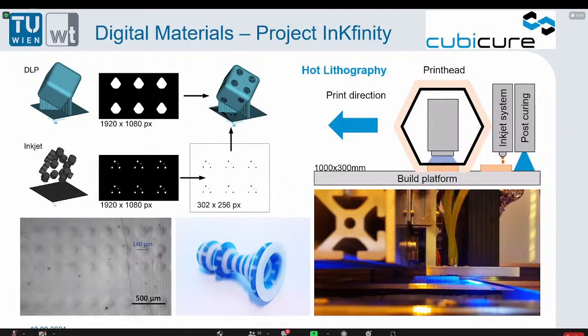Okay, thanks. There's a question from Florent Hanard. Yes, interesting talk, thank you. I was wondering, in the first part of your presentation, you have shown some results on tensile tests, and you compared the reference sample with 100% inkjet, in which you see some softening. But what's interesting to me is that despite the softening, you have some strain hardening capacity. It seems that you are less sensitive to necking, I guess. Have you looked at what's happening within the material? What are the micromechanisms that occur during the deformation, especially at this large strain in the curve?